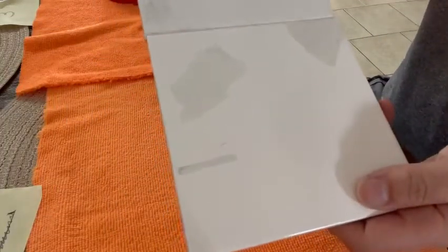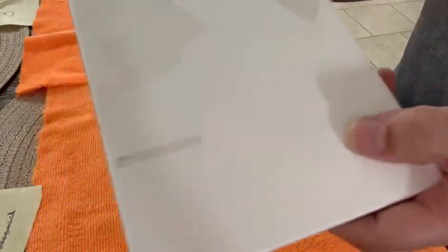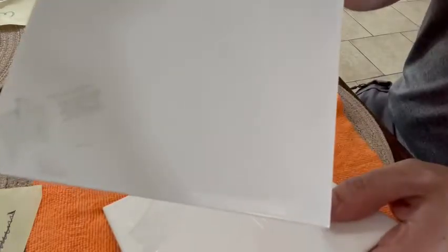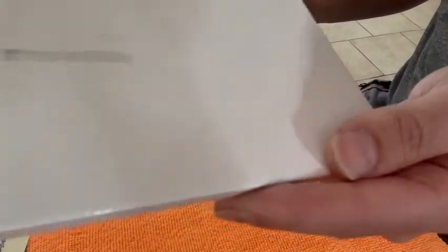So that's the head-to-head. They're both prepped the exact same way. Little triangles popped off on this one. They're both prepped and tested the exact same way. They both have crosslink — both are etched crosslink. This one is Midwest Chemical Prime, this one is Hawk Labs Prime. Both have the same top coat — identical top coat. So this is a 10 out of 10, and this would be like a 9.8 out of 10.